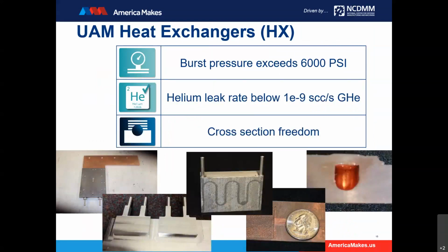As we mentioned, the hybrid nature of the process does allow for things like heat exchangers. And actually our number one commercial product is building heat exchangers of all types. We've built parts that have pressures in excess of 6,000 psi, helium leak rates that are hard to measure. A lot of our helium leak tests we have to outsource because it's such a high hermeticity. And as you understand from other 3D printing processes, you have quite a bit of geometric freedom as to what the device can look like. Additionally, you can mix materials, and we do that often to enhance or optimize the structure. Channel sizes, in the bottom right, you see some channels that are about 10 thousandths of an inch. We've done channels up to several inches.